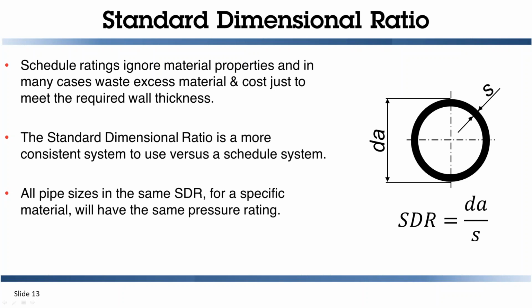So let's take a look at 1/2 inch PVC. Schedule 40 PVC has a pressure rating of about 350 PSI. When you go up to 12 inch, you have a pressure rating of about 80 PSI. Versus polyethylene, SDR 11, 1/2 inch is 200 PSI. 12 inch is also 200 PSI. So no matter what the size, if the ratio of the OD to the wall thickness is the same ratio, you're going to have the same pressure rating. It makes it very easy to design piping systems across a wide size range.